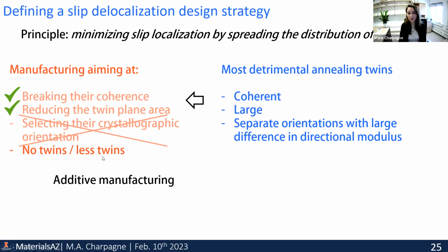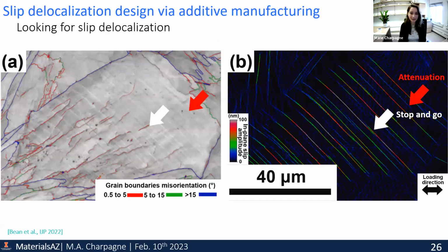But actually with additive manufacturing, we get materials that have no twins or very low twin density. So how about we just look at what happens in these materials? And these are actually very promising. Here is an example in AM316L, so another FCC material, where we see again two of these mechanisms that I mentioned before. The first one being attenuation, where you have a slip band that just dies off in the center of the grain. And again, this stop and go mechanism here in a second region of the material.